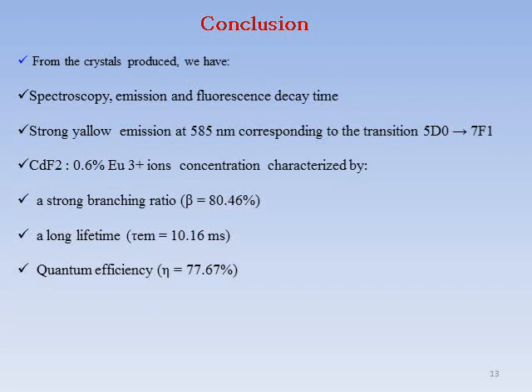As a conclusion, from the crystals produced, we have studied the spectroscopy, emission and fluorescence decay time. We found a strong yellow emission at 585 nanometers, corresponding to the transition from the emitting level 5D0 to 7F1, for the 0.6% europium ion concentration. This concentration is characterized by a strong branching ratio, long lifetime, and quantum efficiency.